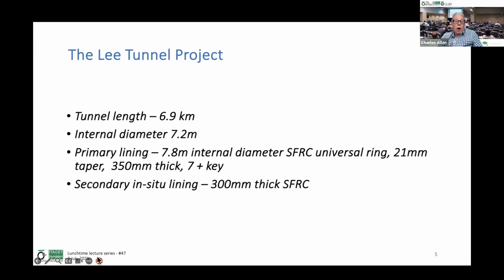Tunnel length 6.9 kilometers, internal diameter 7.2. That included a secondary lining 300 millimeters thick. So the primary lining was 7.8 meter internal diameter steel fibre reinforced universal ring with 21 millimeters taper, 350 millimeters thick, and it was comprised of 7 units plus a key.